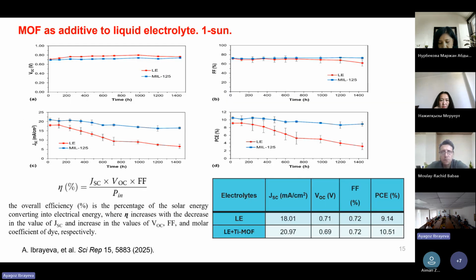And also these devices were investigated under one-sun illumination. On the graph, the first photovoltaic performance was on the first day, and in the graphs you can see that VOC increases after 60 days, fill factor is still stable, and the overall efficiency of these devices decreased because of short-circuit current density.